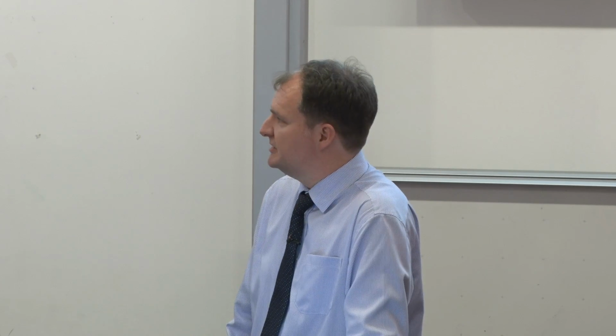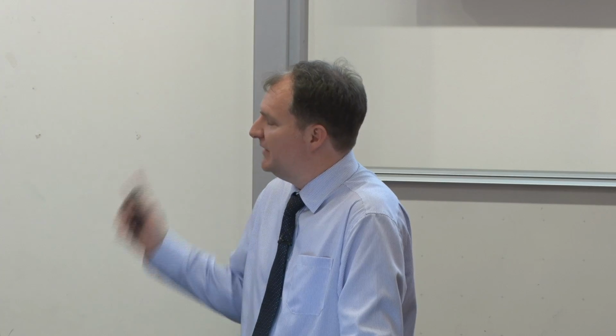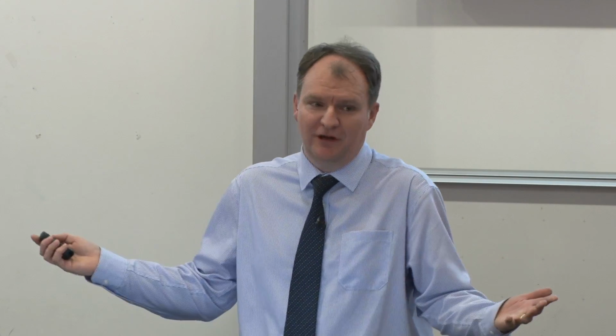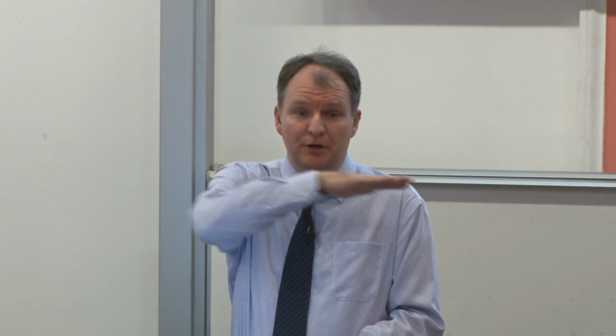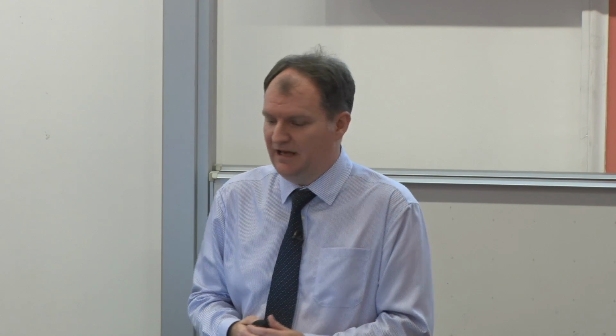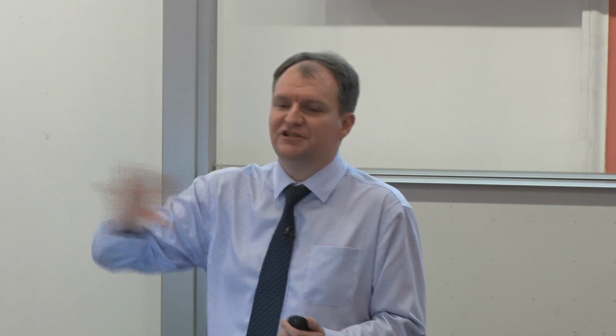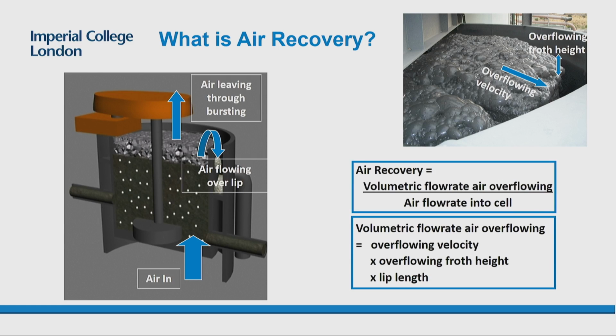And so the most important parameters for predicting the gas behavior are the shape of the flotation cell it's in and the stability of the bubbles. In particular, how much of the air is bursting at the top surface of the froth relative to how much is actually overflowing. We characterize this by something called an air recovery, which is just the fraction of air you put into your cell that actually ends up coming over the lip. And you can measure this by image analysis.